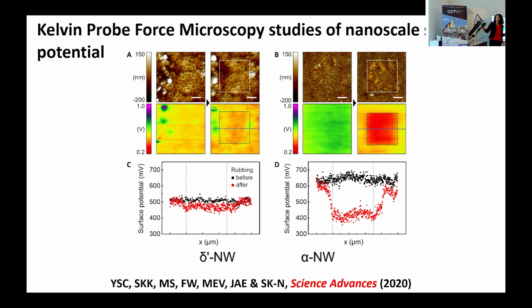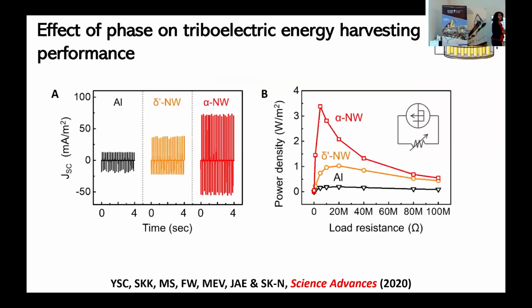And you can clearly see that there's a difference from left to right. The main difference is that on the left, we have what we produced as delta prime nanowires, and on the right is the alpha nanowires. You can see that the alpha nanowires have a much larger transfer of triboelectric charge than the delta prime. So just to recap, the delta prime was great from the piezoelectric point of view, but it looks like the alpha nanowires are actually much better for triboelectric applications.